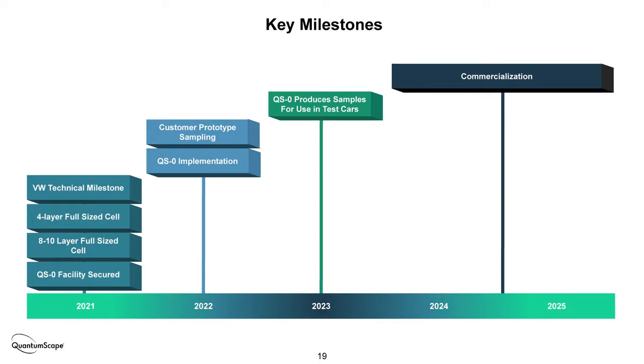We made single layer cells that we showed in December of last year, so a few months ago. By February this year on the earnings call, we had shown four layer versions of that cell, but in a smaller form factor, 30 by 30 millimeters, instead of 70 by 85, so instead of like a deck of cards, it was somewhat smaller. We told our investors that our next big milestone this year is going to be to make those same four-layer cells, but in the full-size form factor of 70 by 85 millimeters.